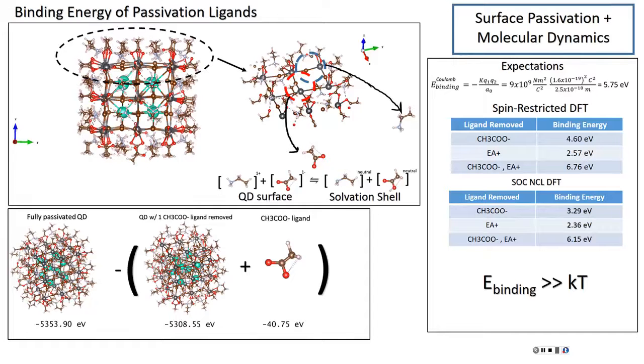Well, can you just use this number of ligands which you use? Right now there is no time for you to do this math on the fly. You can just generally tell that there are anions and cations, both from the core of the quantum dot and from the ligand shell, and the total number of positive and negative charges should total to zero or close to zero. It is one of the principles of how to deposit ligands: deposit them in such proportions that the total charge will be zero, if it is true.